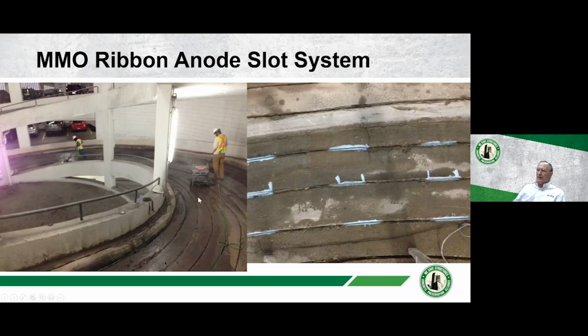Here's a ribbon anode system. This was a replacement of one of the original slotted wire systems. What we did is we came in, and we cut out all the old, well, some of it you could pull out, but a good bit of it we had to cut out. And then we checked for shorts, checked for low cover reinforcement, and we masked off those areas with epoxy.